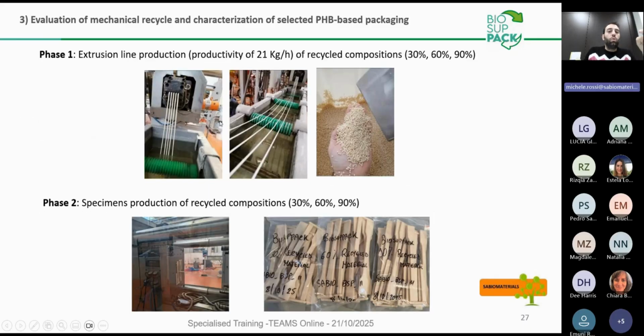In this case, it's not possible to introduce the material directly in the injection molding, but we pass through an extrusion. It means we mix 30% of recycled material and, for example, 70% of virgin material; 60% of recycled material and 40% of virgin material; 90% of recycled material and only 10% of virgin material. This combination has been reprocessed in the extruder, obtaining the pellet, and only at the end the specimens were produced, just to analyze the potential loss or whether the same properties of the virgin material are kept.